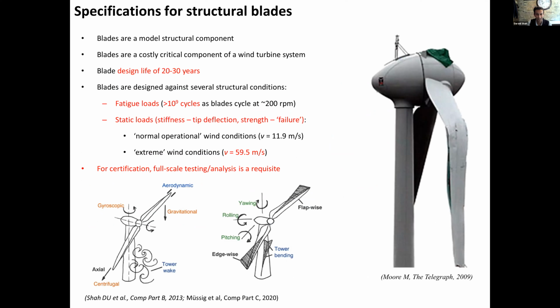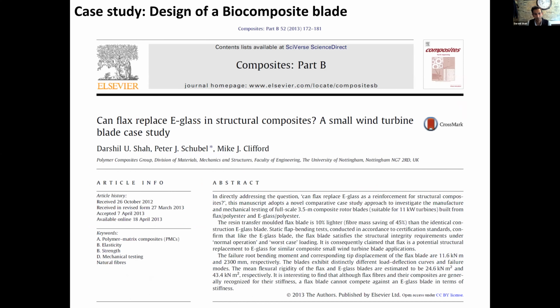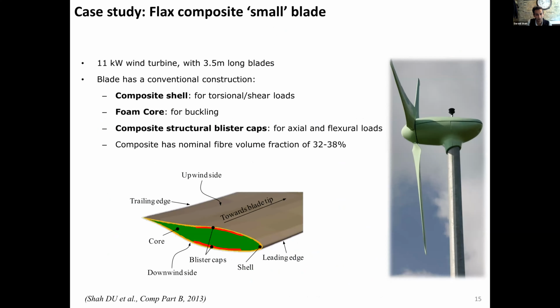So for a structural wind turbine blade, the key parameters that are necessary to design for are their life of 20 to 30 years and fatigue loads. We looked at small wind turbine blades, which actually rotate at 200 RPM rather than 20 to 25 RPM for the larger wind turbine blades. So the fatigue loads can be quite phenomenal, but also static loads in terms of extreme wind conditions, and the fact that these materials need to be tested at full scale for applications. And we have some data on this in a paper if you want to look at that later on.